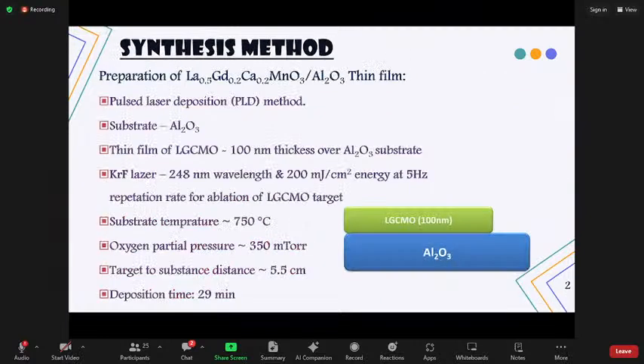So this is the experimental method, or synthesis method, that has been used to prepare the LGCMO, that is LaGdCaMnO3, thin film. The LGCMO film was grown over 001 oriented Al2O3 single crystal substrate by using the PLD technique. The 248 nm KrF laser, with 200 mJ per centimeter square energy at 5 Hz repetition rate, was used for ablation of the LGCMO target, for which the substrate temperature was 750 degrees Celsius, with an oxygen partial pressure of 350 millitorr, and the target to substrate distance was 5.5 centimeters, with a deposition time of 29 minutes.